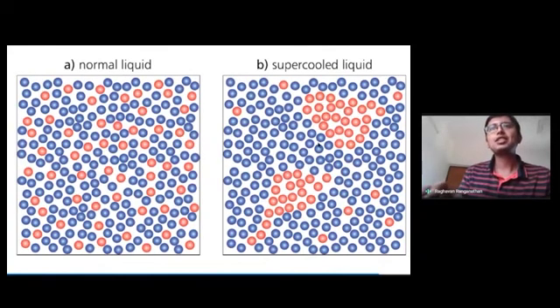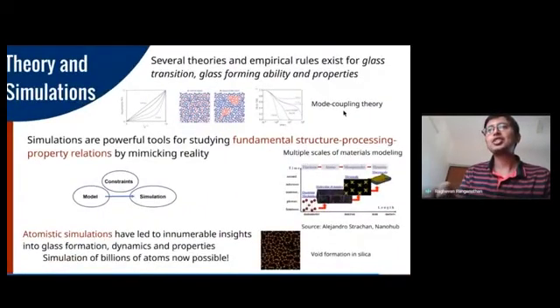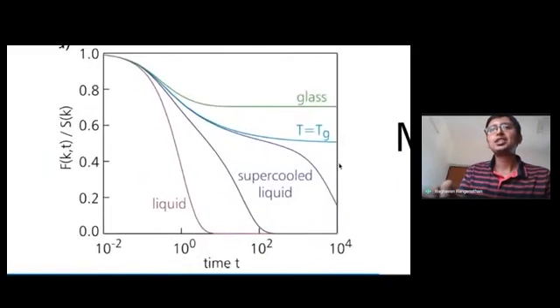And people do see that there are several interesting factors. So there is the short scale ordering in supercooled liquids that you can see by the red spheres. These are small pockets of the glassy liquid that have displaced a very large amount of distance compared to a normal liquid. So these form pockets of regions in space that show enhanced dynamics. And there are several theories. For instance, the mode coupling theory is able to predict the relaxation time of a particular glass. Based on some structural parameters, it can differentiate the time scale for a glass to be formed versus a supercooled liquid and a normal liquid.